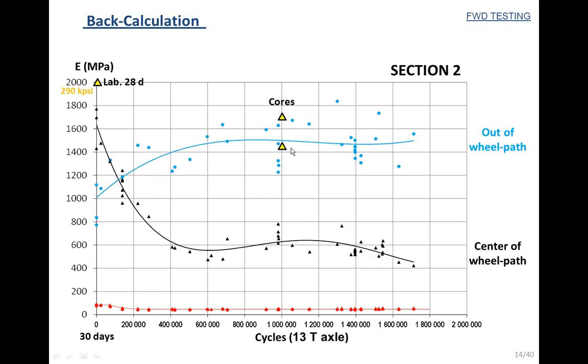You can see here in blue the modulus that we obtained along a line that is out of the wheel path. These black points correspond to the center of the wheel path. So here we have damage, and here we do not have damage. Here we only have moisture effect and aging effect. We also know that we had a compaction problem with this material because this line and this line were built at different moments, the very same day, but not at the same time. The compaction level that we achieved for this path was not very good. So this is why we were obtaining a lower modulus.